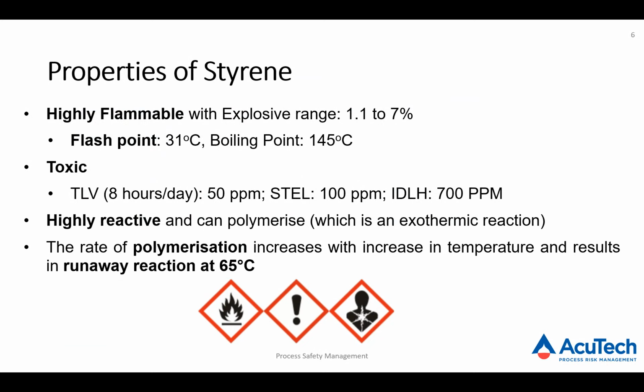These are basic properties of styrene, which is a highly flammable material, which has a flash point of about 31 degrees centigrade. Most of the time, temperature in that part of the world remains closer to that or higher than this. It is also toxic, with exposure limits of 50 ppm for TLV and the short-term exposure limit of 100 ppm, and an immediately dangerous to life and health concentration of 700. This is a highly reactive material and it can polymerize with an exothermic reaction. The rate of polymerization also increases with increasing temperature, but this can certainly be controlled if the inhibitor's concentration is maintained at the required level.